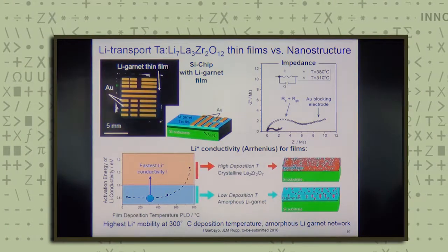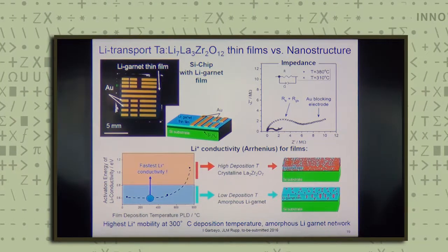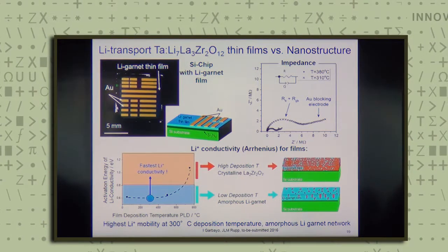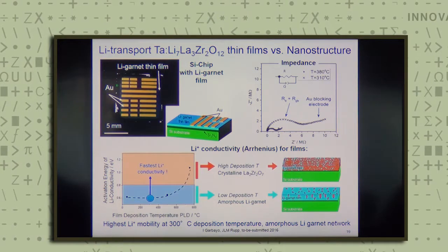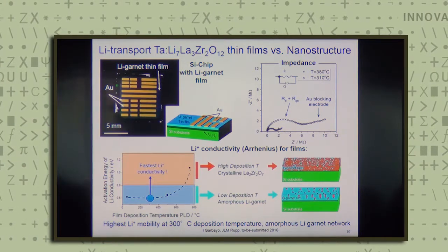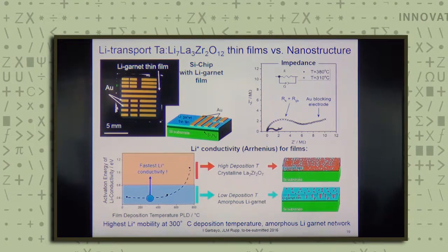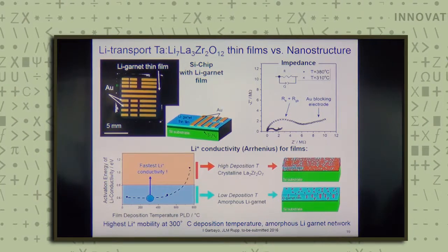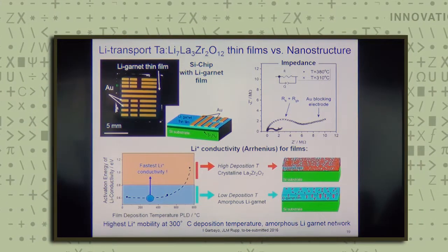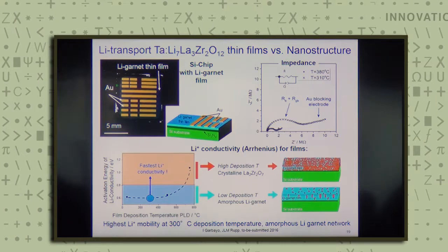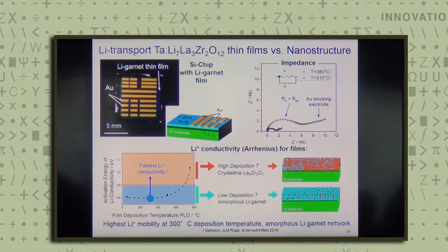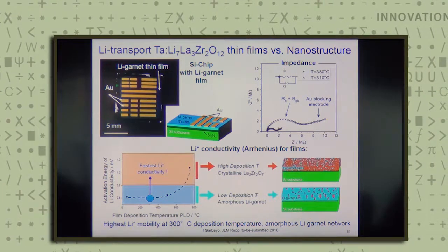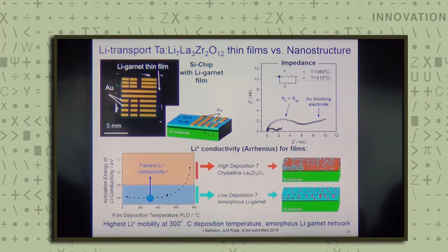Now, what was very exciting for us is that we could see that the fastest conduction, and that's now I think the bad news, is not in the fully crystalline structures. It's really when you're in this glassy, amorphous, thin-film lithium garnet near-order structure. And you can use that to make a low deposition temperature cell where you have, as a compositional point, the thin films that are glassy and have fast conduction.